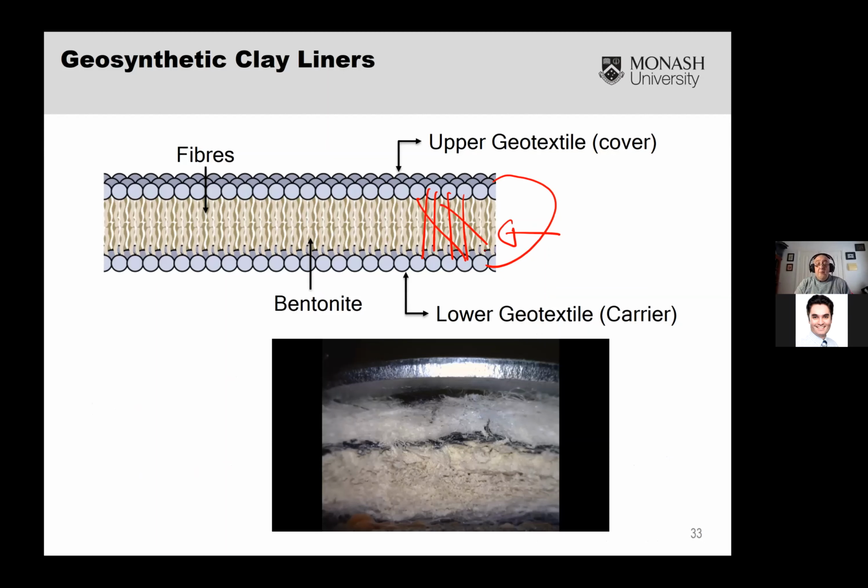Now, the montmorillonite component, which is a significant constituent of bentonite, has a large specific surface area and is capable of both crystalline and osmotic swelling, and it is responsible, obviously, for the desired physical as well as chemical attributes that GCLs are known for. That's why its use is obviously omnipresent in GCLs.